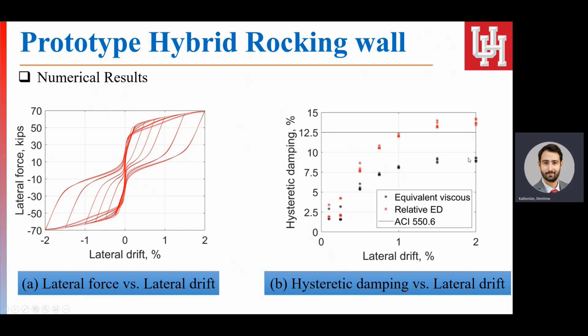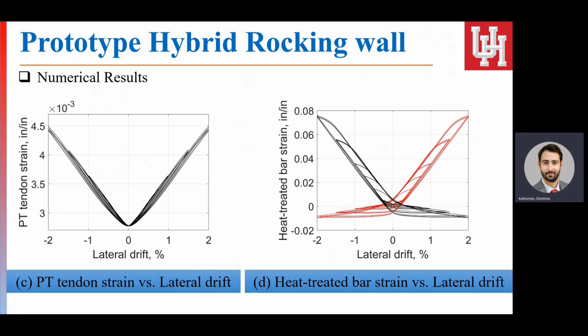And we also plotted the equivalent viscous damping for the system. We also plotted the PT tendon strain. You see here that the wall was designed to ensure that for the 2% drift level, which is a target design drift for this type of walls, the strand is not yielding and is able to preserve its initial strain value, which is achieved in this case.